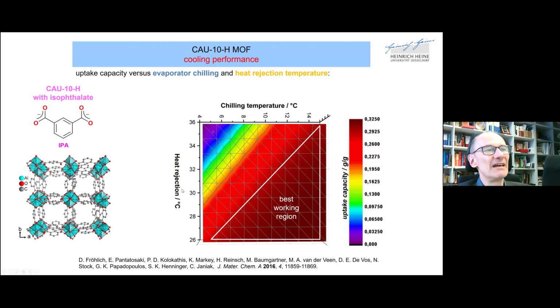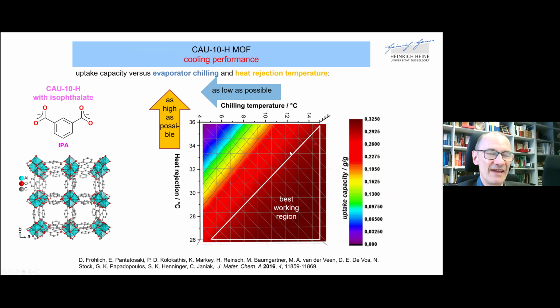So here you see a map which plots the heat rejection temperature, which should be as high as possible, and the chilling temperature to which the water circuit is cooled down, which should be as low as possible. And still the material should have a high water uptake, which is the white triangle here, which plots the uptake capacity in gram per gram. So now this has to be optimized.